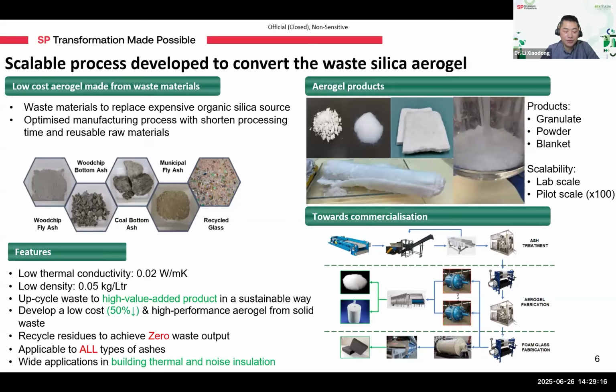So we tackled this challenge head-on by using waste materials as raw feedstock, including different kinds of ashes such as wood chip ash, coal ash, municipal waste ash, and waste glass, and optimizing the manufacturing process to reduce energy consumption and improve yield. As a result, we reduced the production cost by up to 50% and achieved a thermal conductivity as low as 0.02 watt per meter Kelvin, a level comparable with top-tier insulation materials. We also produced aerogel with a density as low as 0.05 kilogram per liter, making it one of the lightest insulation materials available. My colleague Dr. Han will introduce more details later.